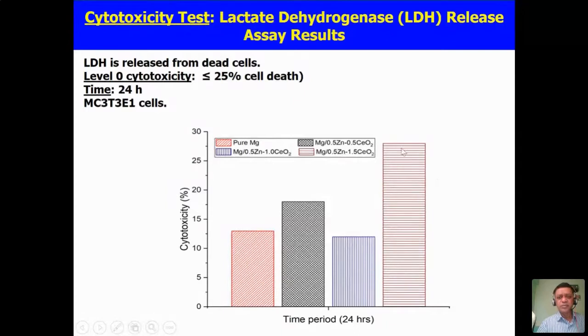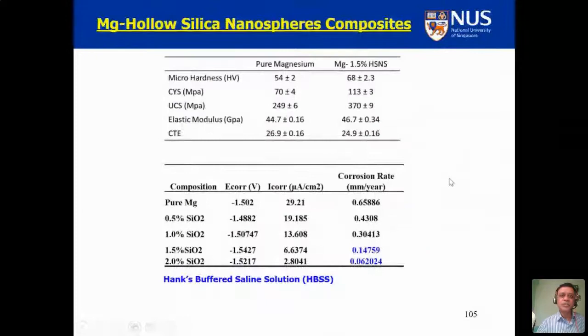Even if it is slightly more than 25%, for example, in this situation of 1.5 cerium dioxide, it is still okay. It should not be the moderate or the severe cytotoxicity. Zero and mild is acceptable. Similarly, we put the nanosilica nanosphere also. And again, you can see that, of course, you see an improvement in the hardness of the nanocomposite, improvement in the yield strength, and improvement in the UCS.